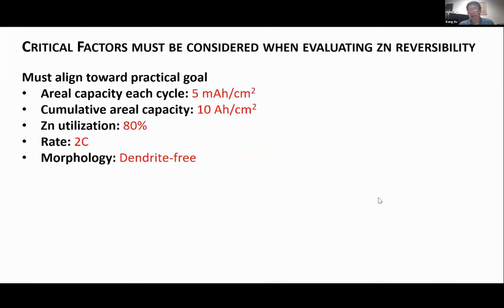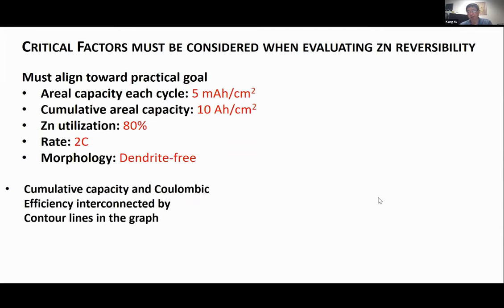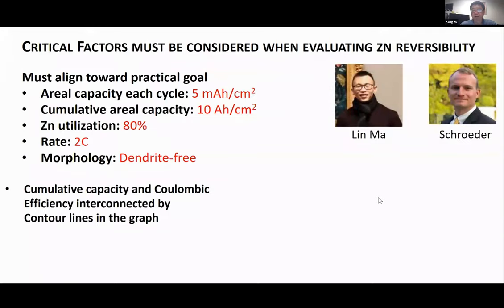So long story short, we examine the different critical factors, and we were inspired by the paper published by Paul Albertus a few years ago for the lithium metal anode. By the way, I would say that most of the issues faced by the metal anodes are very similar. So we think that we have to consider such factors as area capacity, cumulative area capacity, how much zinc you utilize, how much rate you can drain from those, and most importantly, are those depositions dendrite free?